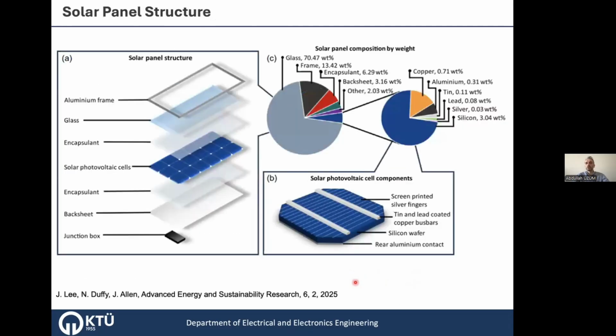So after you manufacture PERC or TOPCon or full BSF structure solar cells, they are serially connected like this. These are serially connected silicon wafers, and they are encapsulated on the front surface and encapsulated on the back surface. They are encapsulated to isolate them from the ambient. And then backsheet, front glass, and the aluminum frame to make it rigid, and the junction box on the backside. And here are the weight percentages of the components, the composition of the solar panel, and you can see that more than 70% of the weight is the glass.